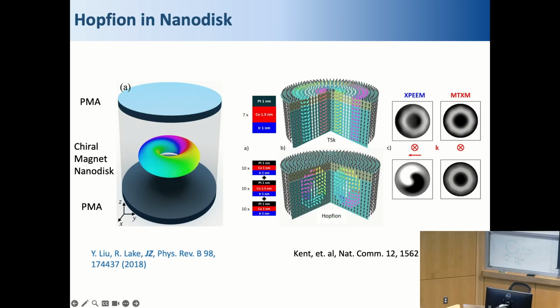Is there any chance that a hopfion can break down into something else like a skyrmion? Maybe, if there is an evolution of the magnetic anisotropy, there will also be an evolution from the hopfion to the skyrmion. Yeah. But mathematically, they're described by different topological indices. A hopfion has this linked pre-image. You need to unlink that in order to make a topological transition and get into another topological class classified by the skyrmion index.